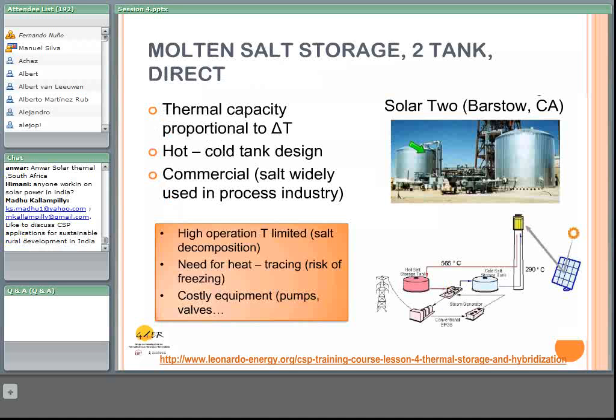This picture is from Solar Two at Barstow. This is the 10 megawatt thermal system, and these are the conditions of the molten salt, with a delta T between the hot and cold tank of nearly 300 degrees. In this case, a little bit less, but in that range. And the maximum temperature must be limited, because above these temperatures, this mixture may experience some decomposition.